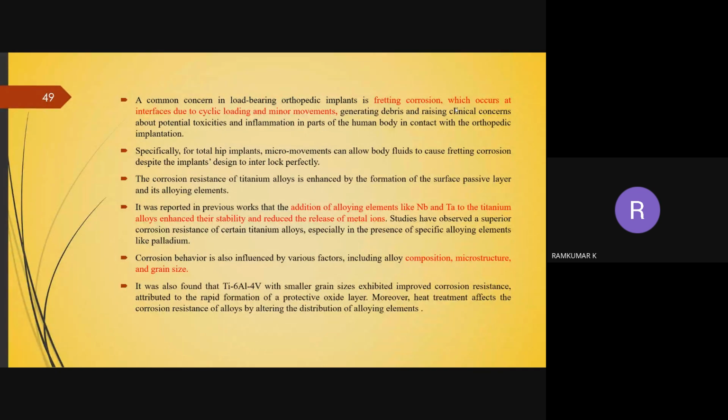This corrosion can be reduced by addition of alloying elements like niobium and tantalum to the titanium alloys. This addition of niobium and tantalum will reduce the release of the metal ions. The corrosion behavior is also influenced by its composition, microstructure, and grain size.